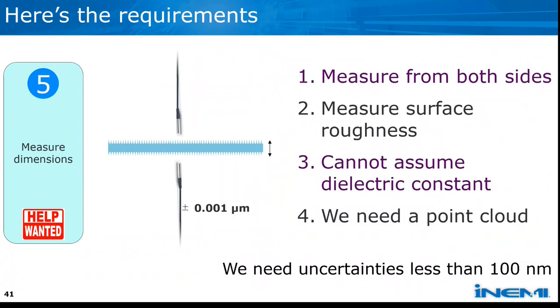Now, I said that this technique was something that we thought was the best measurement technique. We're interested in learning if there are other better measurement techniques. The key metrics for using this measurement technique are to know that you have to measure from both sides. If the material has some warp or bend in it, then you need to be able to measure that thickness accurately, right? So if you're only measuring from the top, and you can imagine that the material is cupped, then you might convolve the shape of the material into your thickness measurement, and that might perturb your results. So you really need to measure from both sides.